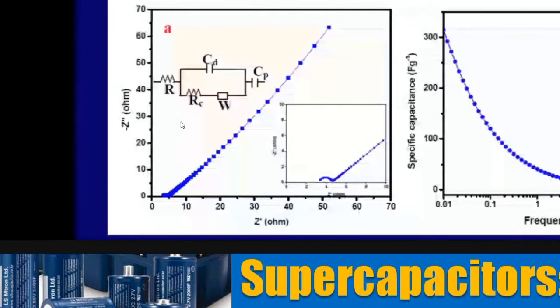You will see that the real part and imaginary part are plotted, and the extended scale that you see as an inset shows a small semicircle which actually indicates the charge transfer resistance. You can see that it's about 3 ohm, which is an excellent thing, and we try to calculate this value again by fitting this impedance data to the equivalent circuit.